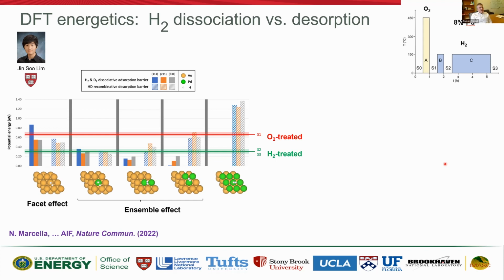So when theory can start with just a few models, it's much better than having an arbitrary starting structure. And in this case, we had very limited possible ensembles to consider because this number was constrained by our X-ray measurements. And so, as you see, considering different processes of hydrogen or HD exchange, starting with the dissociation of hydrogen and deuterium, the recombination, all these energies were calculated and are shown here as the vertical bars. And they're calculated for different surfaces, 111, 211, 331, as different colors.